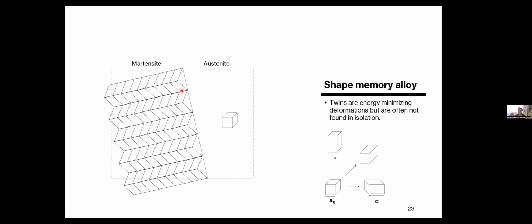So the origin of microstructures in these shape memory alloys is associated with the fact that each of these lattices can fit together to form finely twinned microstructures. This is something you see when you look at a micrograph of a shape memory alloy. This is a uniform phase, the austenite phase, and a pretty sharp interface, this is the martensite phase, which is a lower symmetry phase, but essentially this phase has a fine mixture of twins.